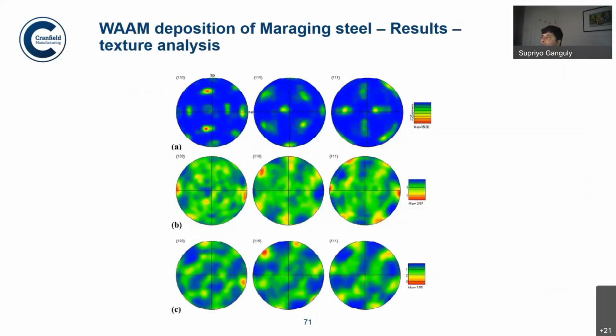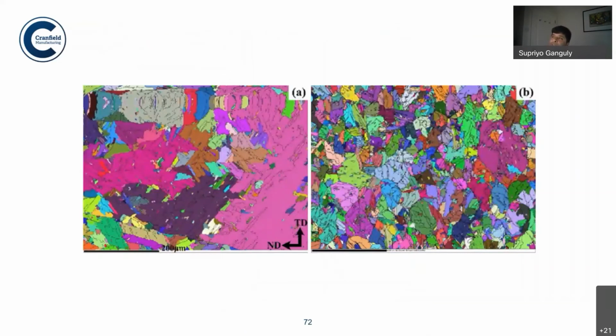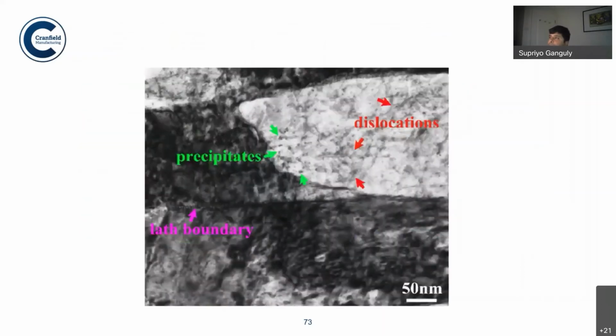So these four figures are showing that if you see the top one, the intensity is 15 times the random texture, whereas the bottom ones show that with different levels of rolling, it is now reduced. So basically the alloy is becoming much more isotropic and without much texture. This shows the grain structure; on the right hand side is the rolled one, and you can see the texture is becoming much more randomized. And this is the structure after heat treatment, where the precipitates are quite clearly shown, and some dislocation densities can also be visible.